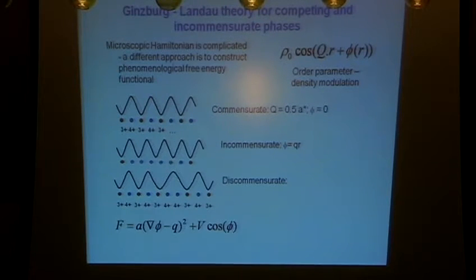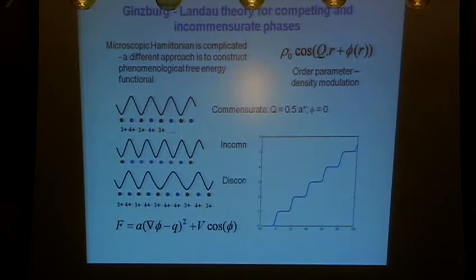So what that means is I would end up with a picture with a phase, we go with a staircase like this. And by the way, the minimal model from symmetry grounds, which gets you this, is actually a Hamiltonian, which couples this density wave to the underlying lattice with a periodic potential, and then has an elastic term which wants to stretch it to its perturbed wave vector. And a minimum of this Hamiltonian produces something that looks like that. And the shape of this curve, how well defined these peaks are, is associated with the relative magnitudes of these vectors.